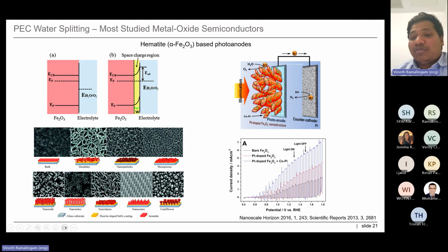Here is another example of Pt doped iron oxide nanostructures, where when they dope Pt into this iron oxide, you can see better performance compared to the bare system. You can see that there is an enhancement in the current density, for example, from 2 milliamps per centimeter square up to 7 milliamps.